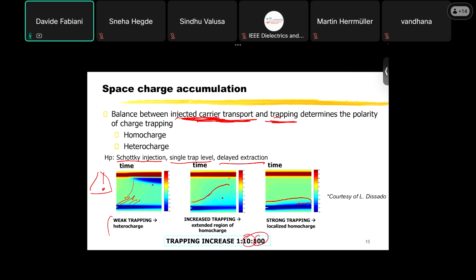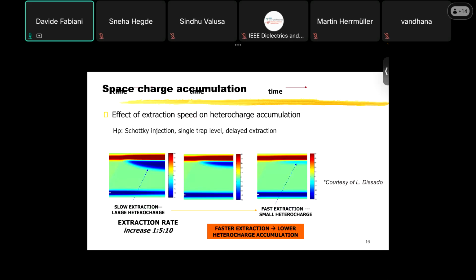So playing on the trap depth, you can modify the trapping mechanism inside your insulating material. Or you can also modify the extraction rate. For instance, if you increase the extraction rate by a factor of 5 or 10, you can see that the heterocharge accumulation is reduced significantly. So you can play on injection, extraction, and trap depth, okay? In that way, you can change the space charge accumulation features of your insulating material.